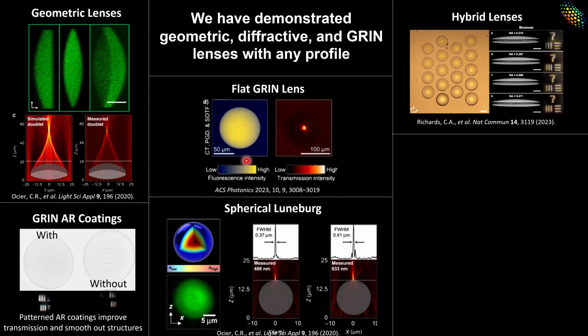So this is, I believe, the first published example of a visible wavelength spherical Luneburg lens, where a Luneburg lens is a specific spherically symmetric refractive index profile that has the interesting property of taking collimated light from any direction around the sphere and perfectly focusing it to the opposite side of the sphere without any chromatic or other aberration. Oh, perfectly? I mean, in theory, fully perfectly. In practice, there are always deviations and errors. But what this is showing is 488 nanometer light, and this is 633 nanometer light, and they form basically fully diffraction limited spots on the opposite side of this sphere, just from this single element.